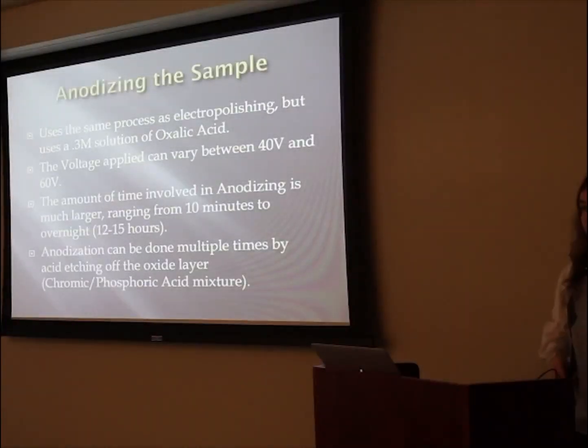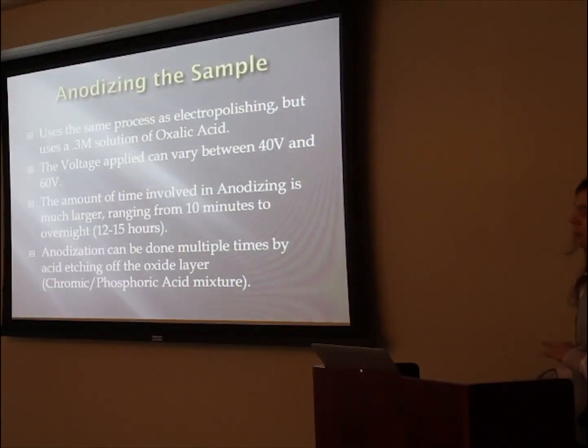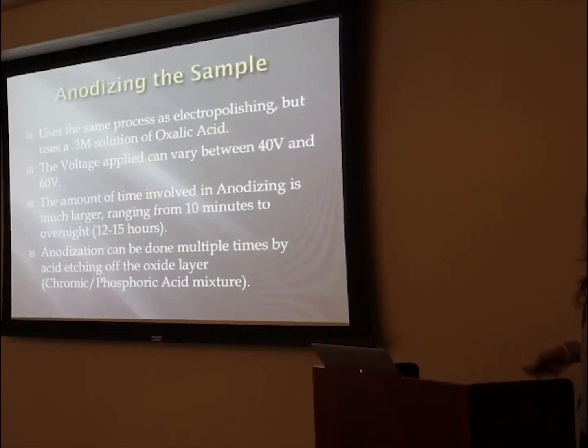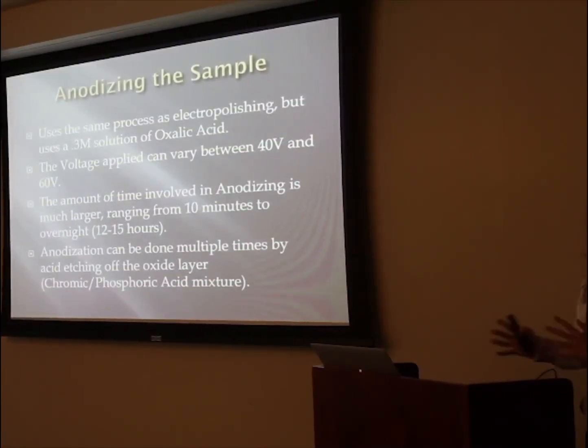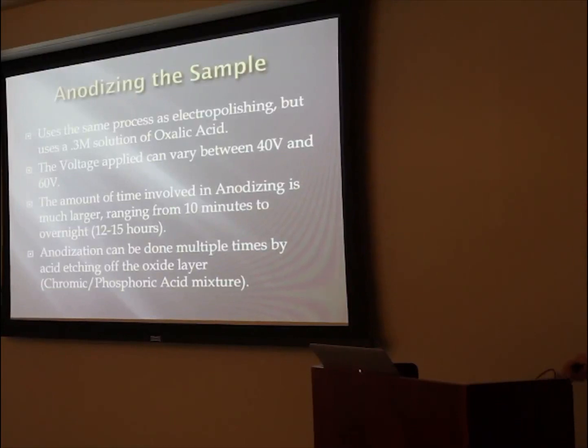So after you electropolish it, the next step is to anodize it. So instead of using an electropolish solution, we use 0.3 molar oxalic acid, and we use voltages varying from 40 volts to 60 volts. So then, along with those parameters, we also care about how long the anodization lasts. So that can last anywhere from an initial small 10-minute window to possibly 12 to 15 hours overnight.